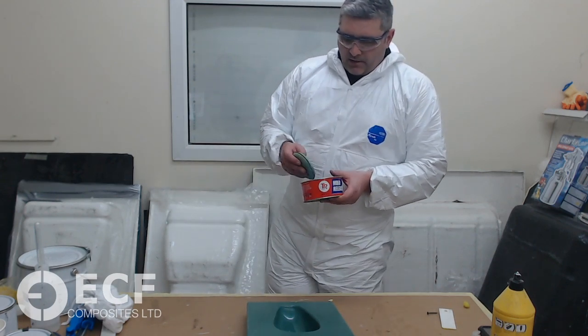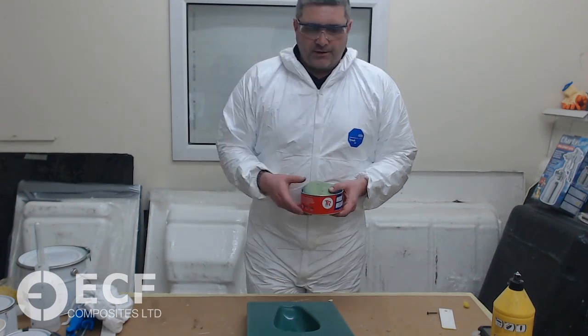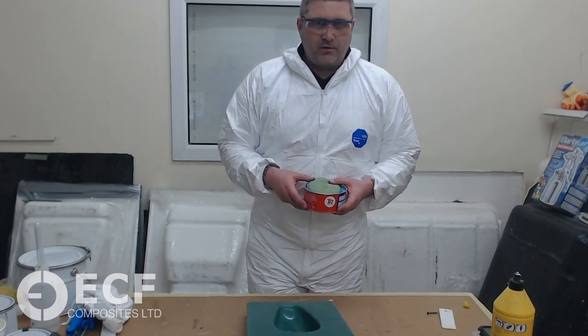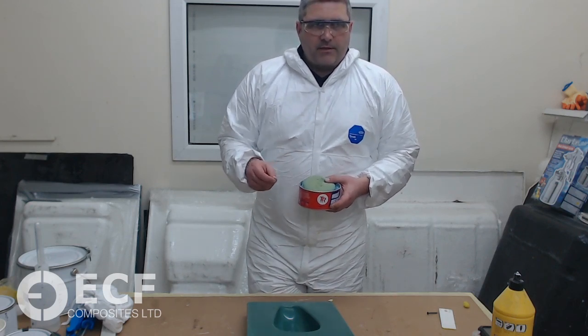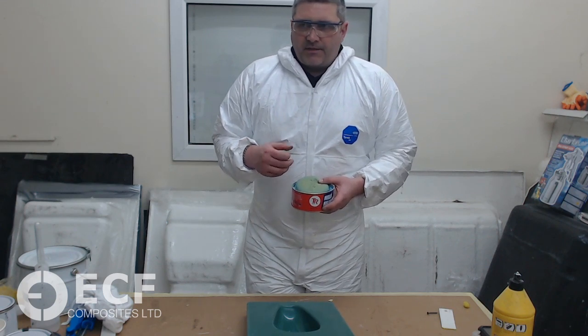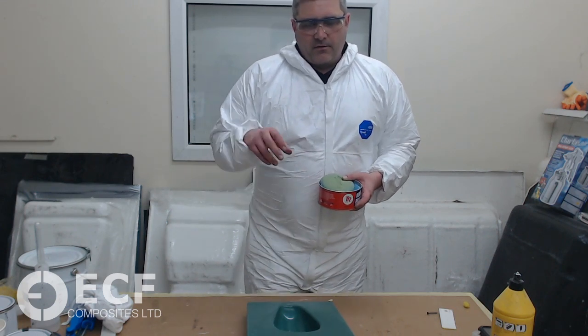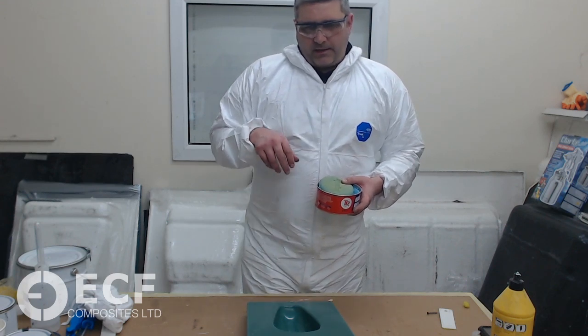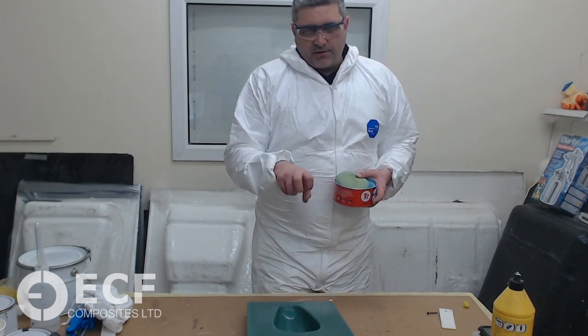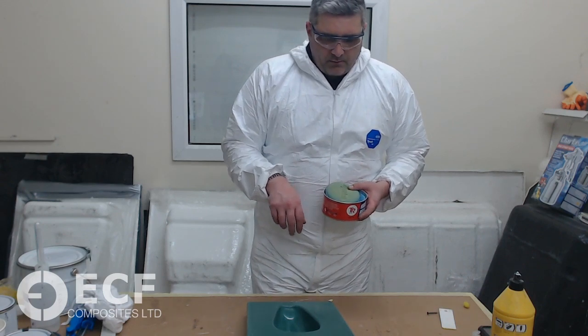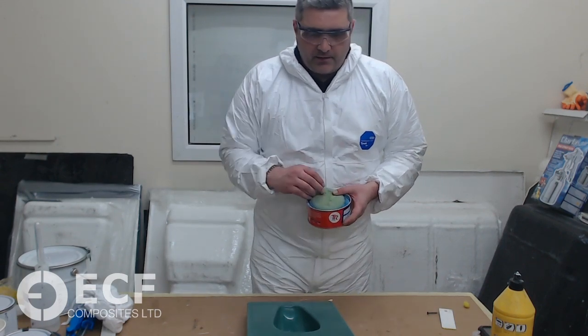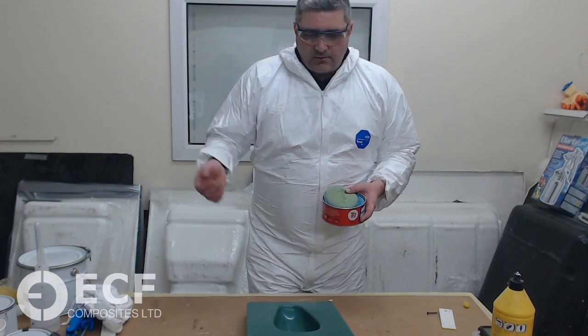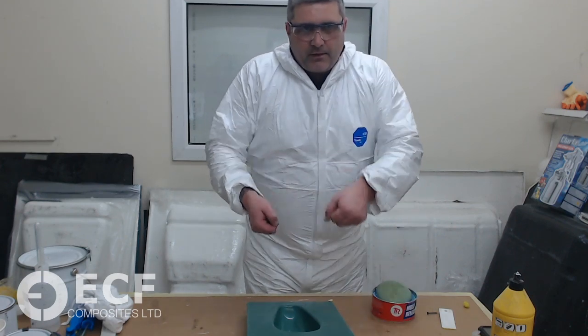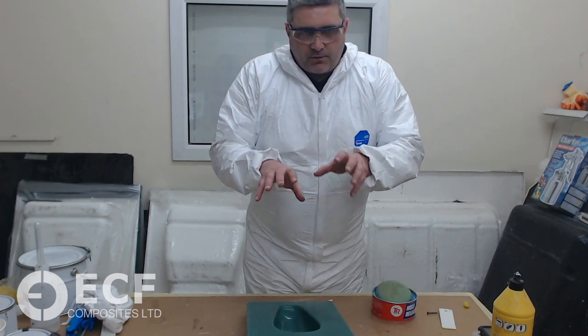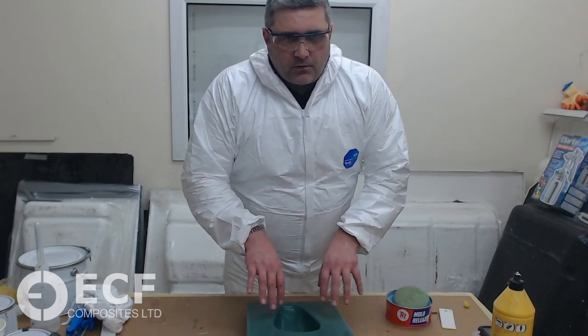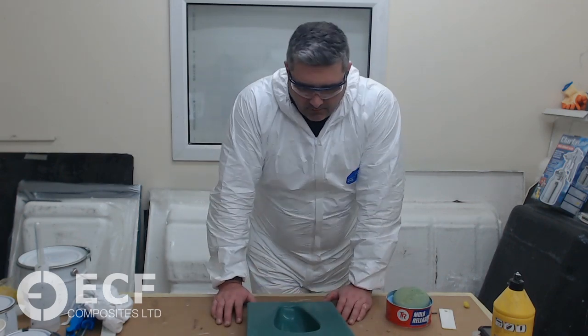You can use T-cut. Years ago when I first started in the factory here, we used to use T-cut a lot. The only downside to T-cut is it's designed for car paint rather than hard gel coats, and if you buff too much with T-cut you can actually burn the surface, which was a common thing back in the factory that I was aware of during the 90s. If you polish it too hard, it would just burn the actual gel coat, which in a sense is a plastic.